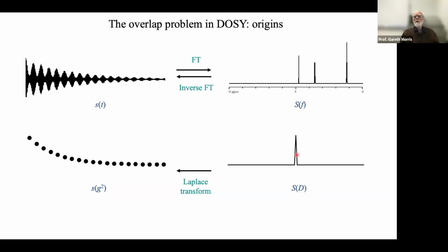If we have a sample which has some particular distribution of signal strength as a function of diffusion coefficient, and we do a diffusion NMR experiment, we measure, often very accurately, a decay of signal as a function of gradient, here of gradient squared. The relationship there isn't a Fourier transform, but it's the same thing without the square root of minus one. It's a Laplace transform. And so we might reasonably think, well, what's the problem? Let's just do an inverse Laplace transform.